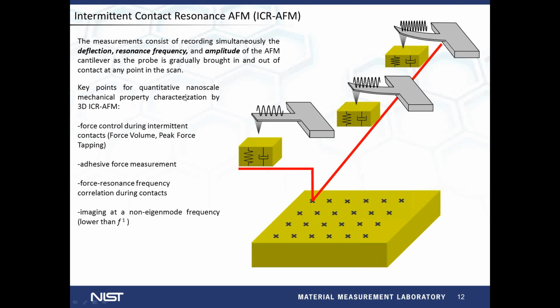And to get quantitative measurements out of this technique, we are looking for a few key requirements. We need force control during intermittent contacts. This can be achieved in force volume and peak force tapping. We also need adhesive force measurements to be used in the subsequent analyses. We also want to be able to correlate the force and resonance frequency measurements during contact. And lastly, we want to scan at a non-eigenmode frequency to minimize the cross-talk. All of these requirements are met, as I said, in both force volume and peak force tapping modes, but not in other intermittent modes like tapping mode AFM, for example.